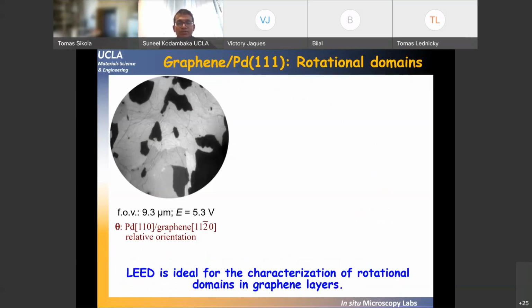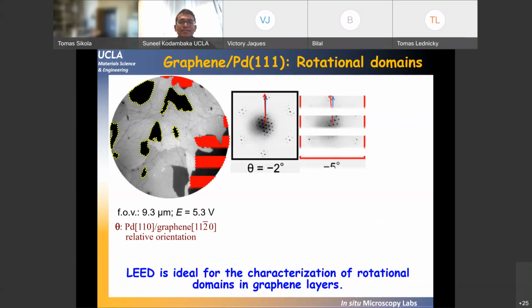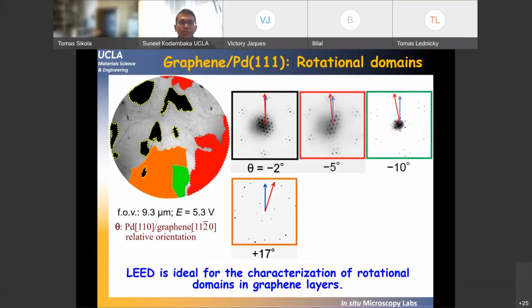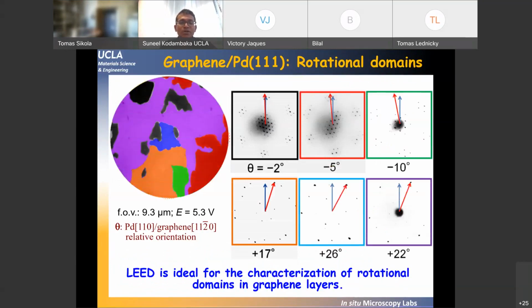And now I'm going to show the rotational domains that exist when you do an uncontrolled heat and cool of the sample. So these are selected area low energy electron diffraction patterns that are color coded for clarity, obtained from different regions on a given monolayer covered area. And as you can see, and I won't go into the details of the moire patterns that you observe, the red arrows correspond to the graphene domain, and the blue arrows correspond to the reference palladium 111 surface. And the magnitude and the direction of the arrows correspond to the relative orientation with respect to palladium, either plus 17 degrees or minus 2 degrees, meaning how they're rotated to the left or to the right.